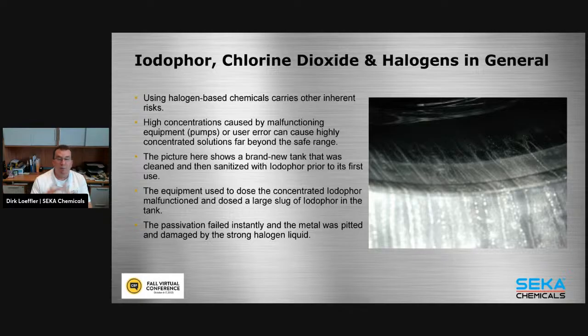But still today, I come into breweries that use iodophor or chlorine dioxide as their primary sanitizer and do not rinse. These are products that cannot be used without a final rinse on stainless steel, period. There is no if or but. You will damage your equipment, you will get pitting, you will damage your stainless steel. There is no if, there's only a when. So be aware that if you use chlorine dioxide, iodophor, or bleach, it will pit your tank.